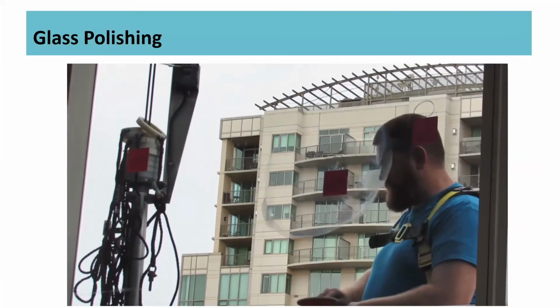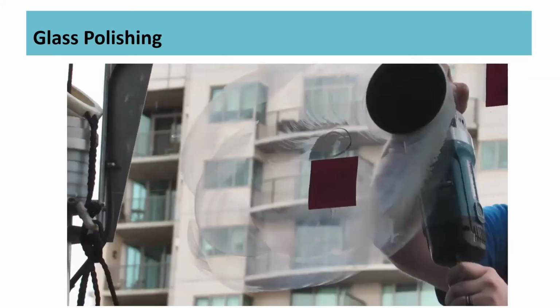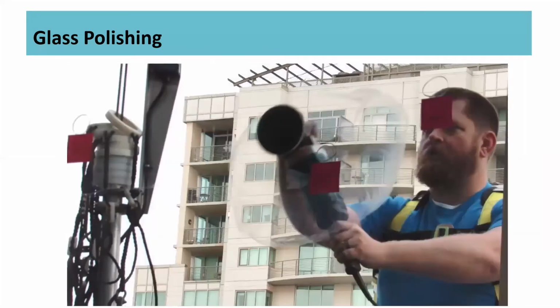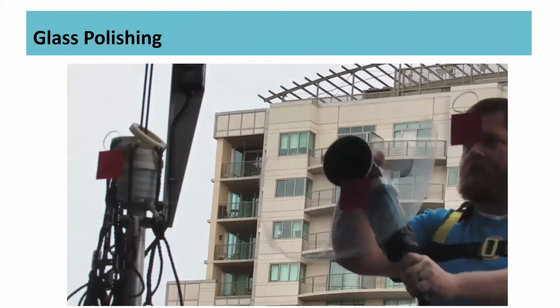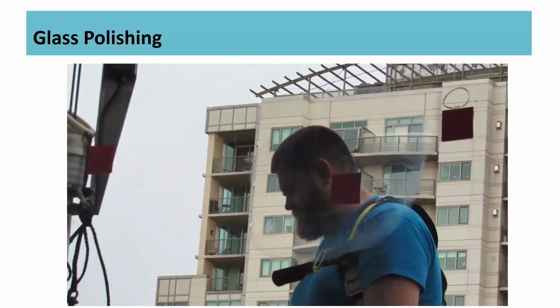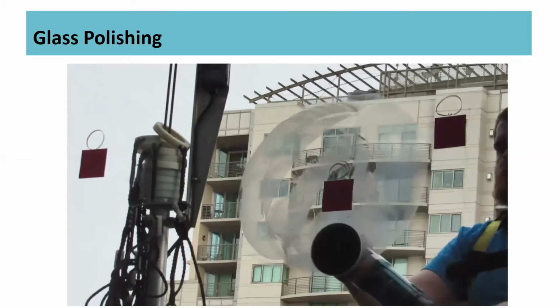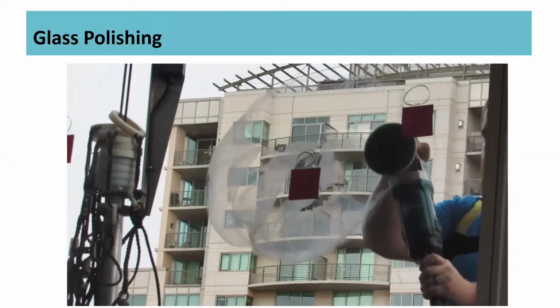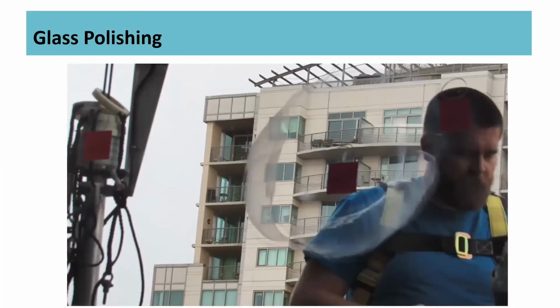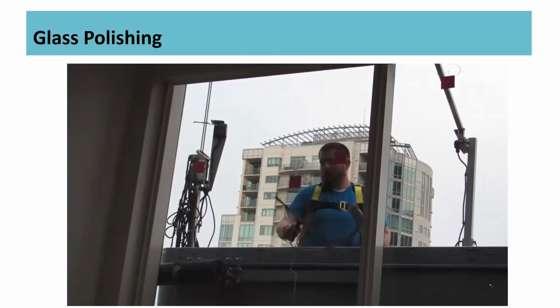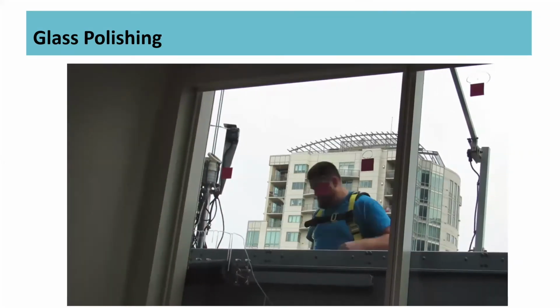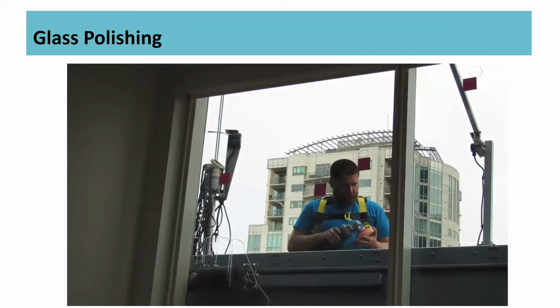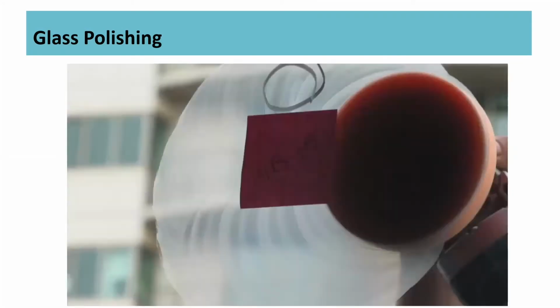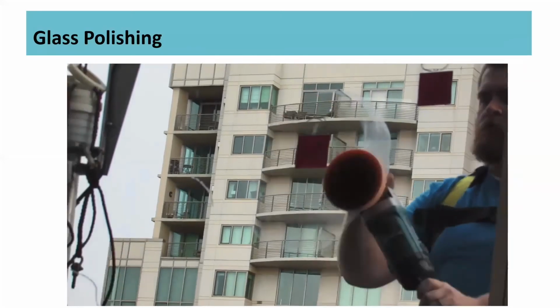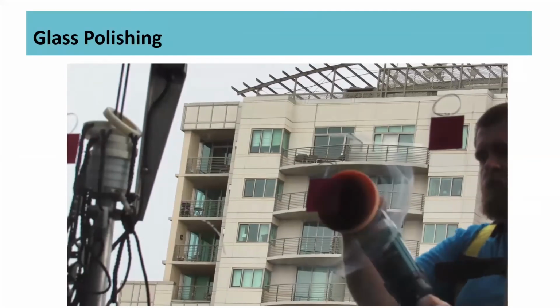So here he is in the final process using a cerium oxide solution on a felt pad on the end of a polisher to restore the glass to optical clarity. And he's making it look pretty easy, but as we've noted, it's not as easy as it looks. As part of the final process, he's going to use a mop head and a squeegee just to make sure it all looks good. And lo and behold, he found an area that he's not pleased with. So he diligently goes back after it. So there's no indication of the glass blemish after he's done.